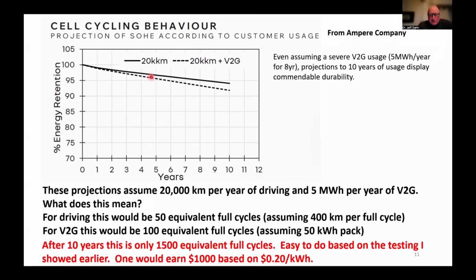And then the dash line shows what would happen if you, in addition to the driving 20,000 kilometers a year, you also did vehicle to grid service. And assuming the vehicle to grid service was 5 megawatt hours per year for 8 years. So then you say, okay, what does 5 megawatt hours per year mean? Well, for the vehicle to grid, if you have a 50 kilowatt hour pack, to store and deliver 5 megawatt hours, it's only 100 equivalent full cycles. Again, that's nothing. So after 10 years, the accumulated use is only 1,500 equivalent full cycles. And I'm showing you things 26,000 cycles with 87% remaining. So this is fully believable.